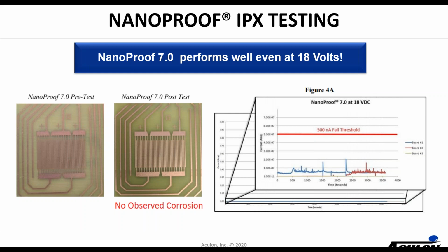Yes, absolutely. So what was done here was this IPX test. The board is essentially coated with the coating and is then inserted into salt water. It is powered up, and the current leakage is then measured. And so you can see on the right side of the screen, this is measuring the current leakage. As these are powered up and in water, the coated board is ticking along somewhere around 100 nanoamps, and 500 nanoamps. Any spike above that 500 nanoamp is considered a failure threshold. So these are well below the failure threshold.